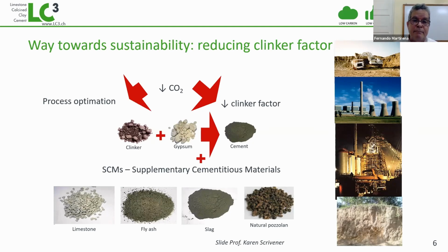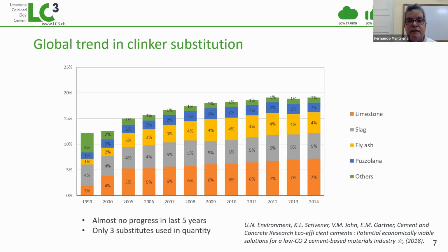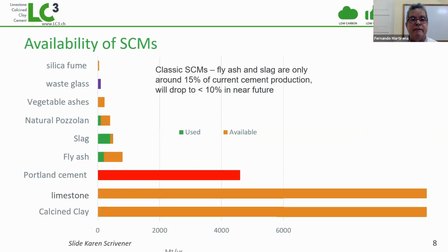We also have limestone, natural pozzolans. But what we're seeing in the last few years is that there's a plateau in the clinker substitution rate. On one side, because if you increase the clinker substitution with these normally used pozzolans, you compromise strength, especially early age strength, and that's bad for concrete. But the most important thing is that the availability of many of these supplementary cementitious materials is not in the same order of magnitude as Portland cement production in a year, as you can see here.